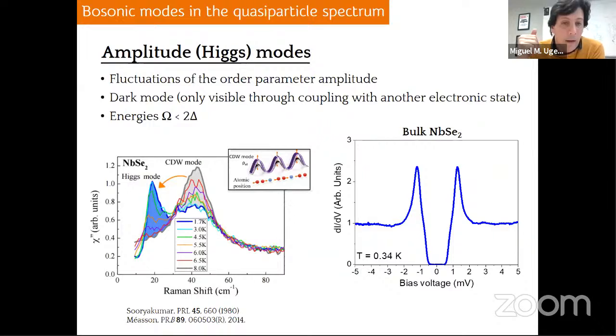So basically, the reason why this mode has been observed in niobium diselenide is because this Higgs mode is coupled to the charge density wave and becomes visible. The problem is that, if you see here on the left, this is the density of states for bulk niobium diselenide, and the effect of this Higgs mode has, in principle, no effect on the density of states. So that's why we believe, among other considerations, this is not the only reason, but it's an important reason, why we believe this cannot be Higgs modes either in the single layer limit.